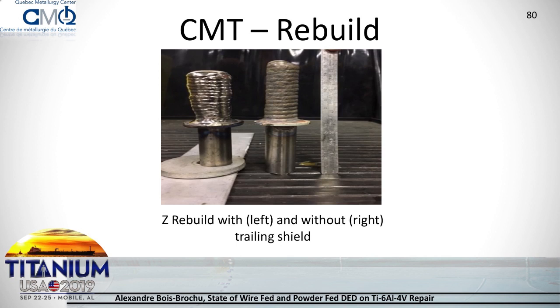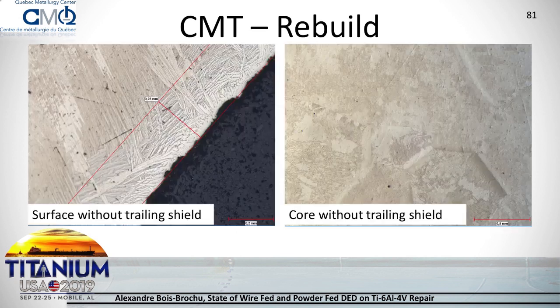So the actual melting pool is protected by argon, by local shielding, but on the left you see using a trailing shield provides very low oxidation. On the right, you see the surface is oxidized. But if you look at the microstructure, the actual alpha case is only 250 microns thick.